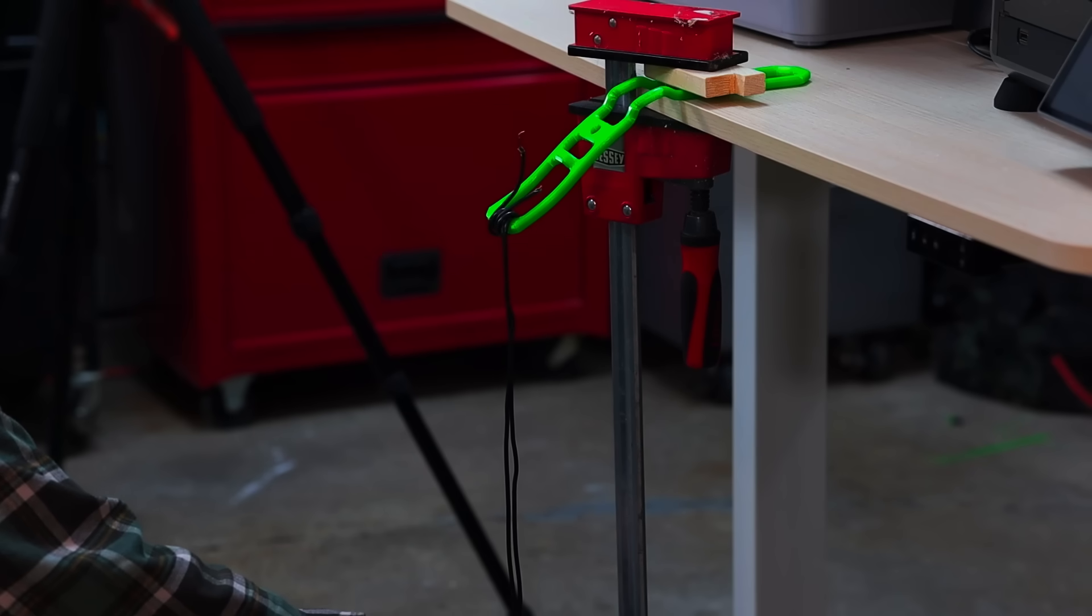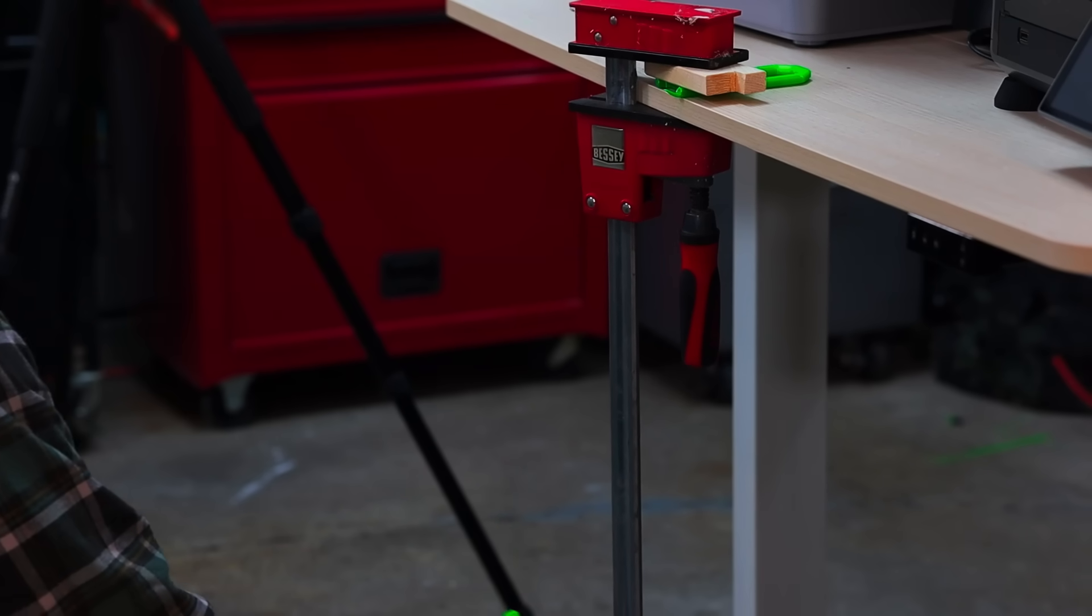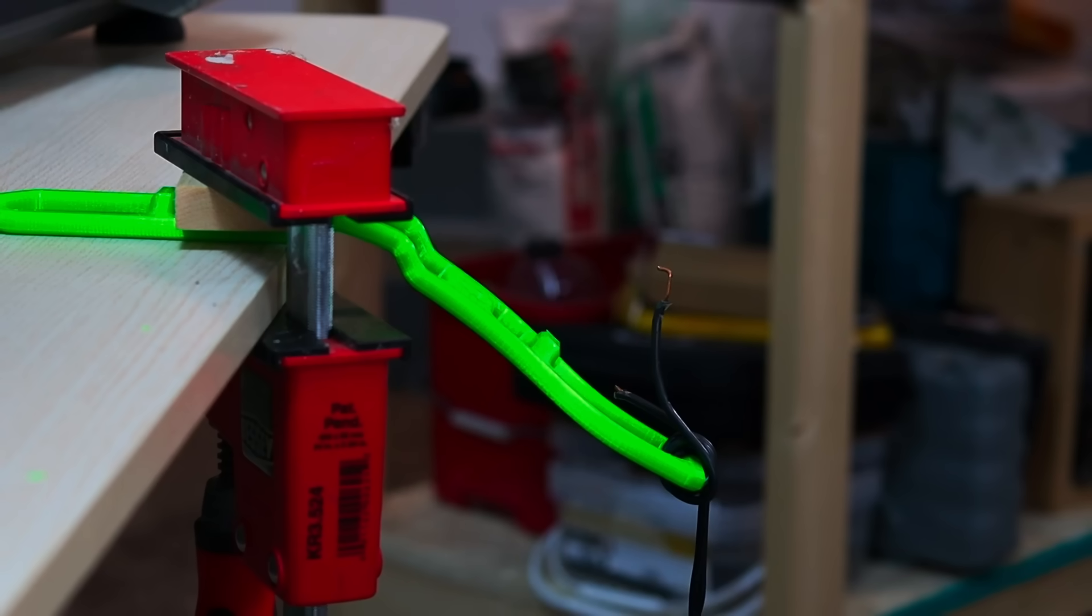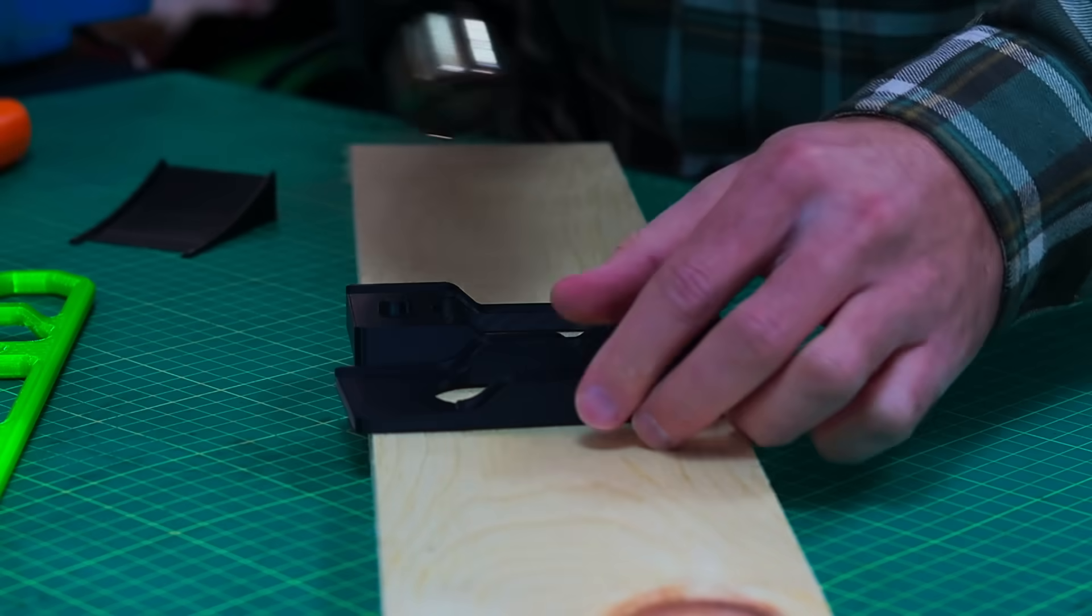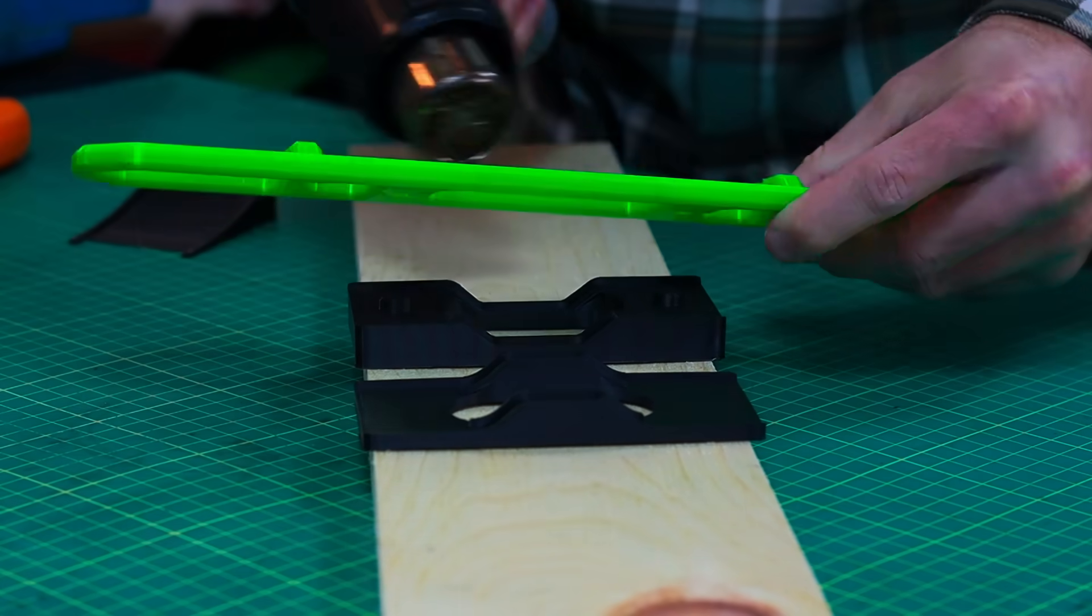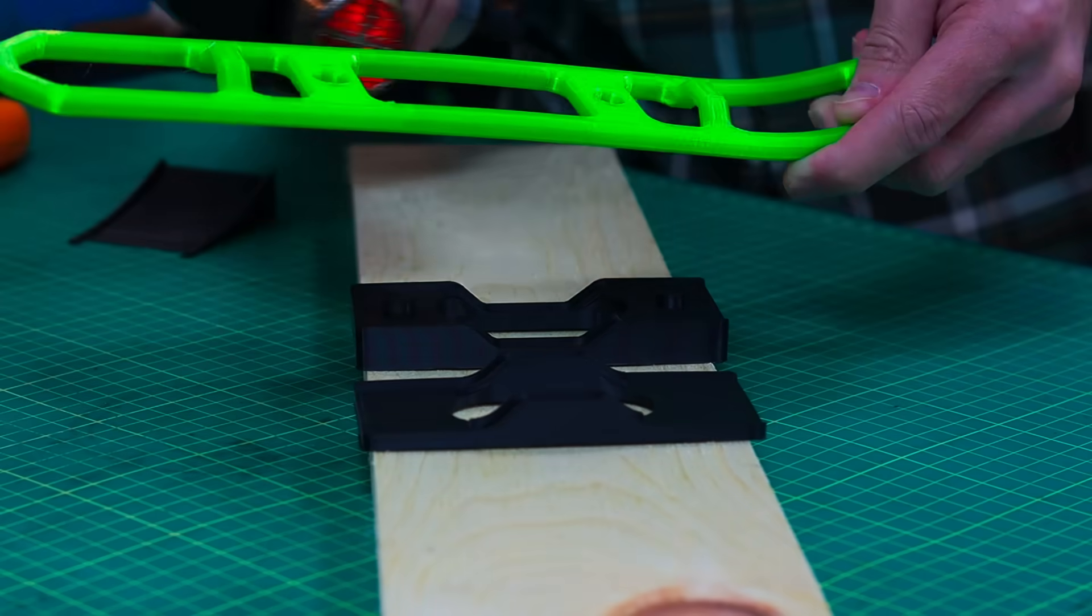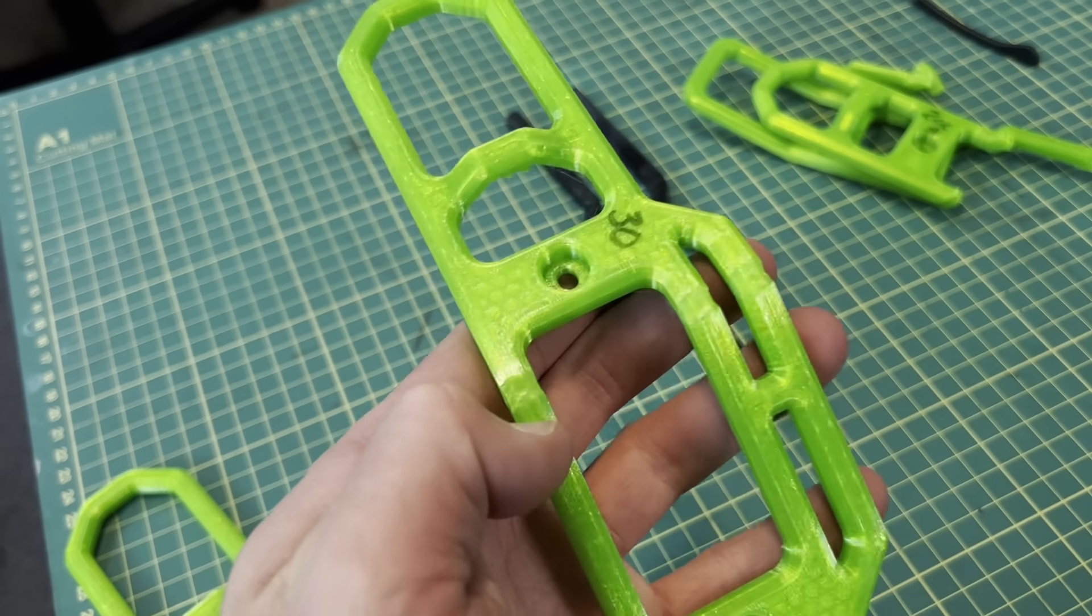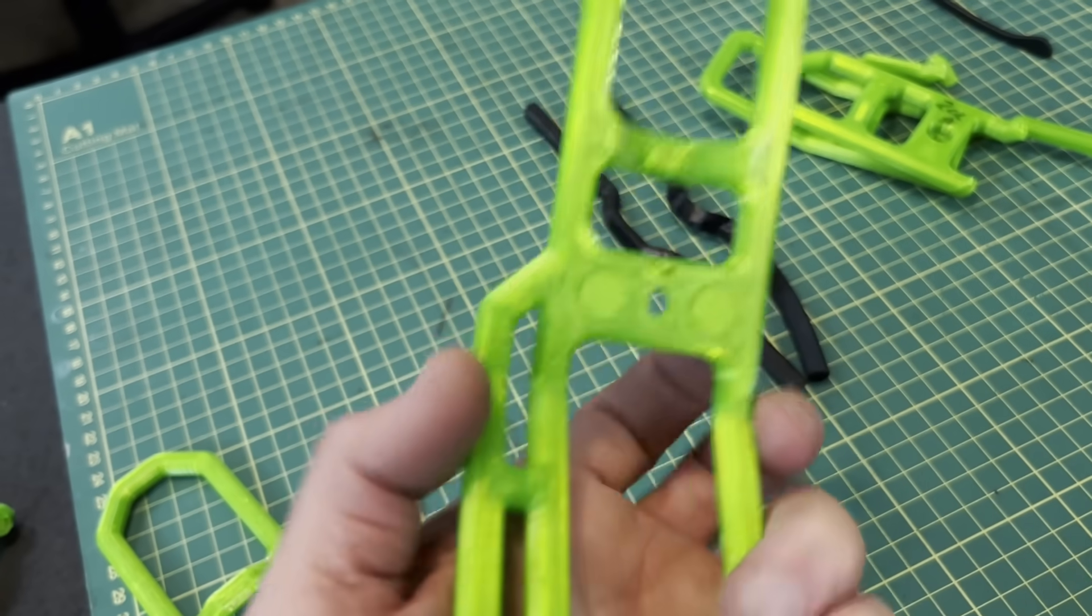Mod three, our experiment didn't go as I had hoped. I think we have a combo of issues here. One is that I made the middle far more rigid, again concentrating the stress. In addition, heating the material like I did probably weakened it. I would have been better to create a full ABS form and then anneal it in the oven and let it cool slowly. And that's okay. We still have a clear winner and that's mod number two which will be uploaded as the remix.